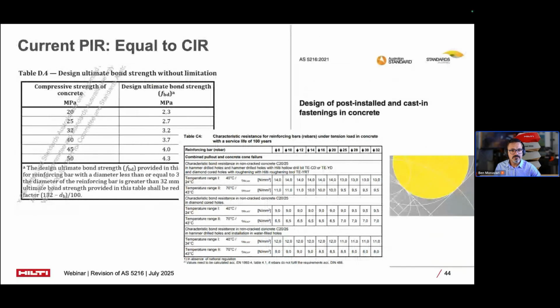The current equal to casting approach assumes that post-install rebar performs identically to cast-in reinforcement. While conservative, this approach has significant limitations. Bond strength of, as an example, the RE500V4 chemical anchor can achieve up to 14 MPa. However, AS 5216 limits the usable bond strength to match cast-in bar allowable values, which is typically around 2 to 4 MPa, depending on the concrete strength. So obviously, we're not utilizing the full capacity of the chemical in our post-install